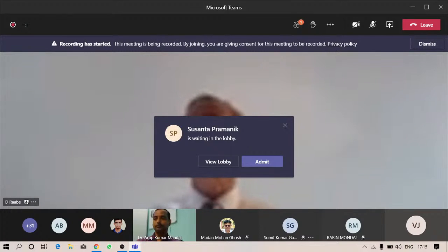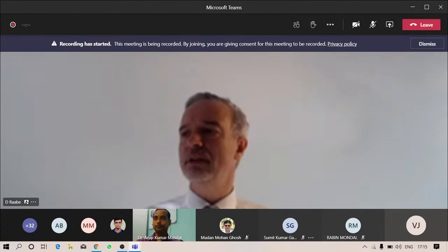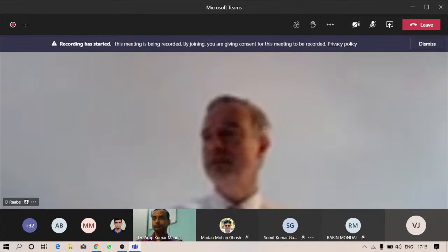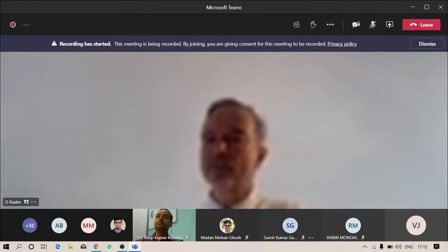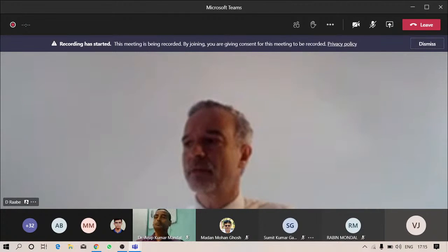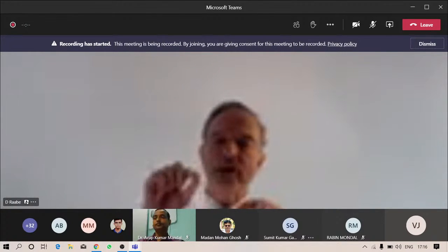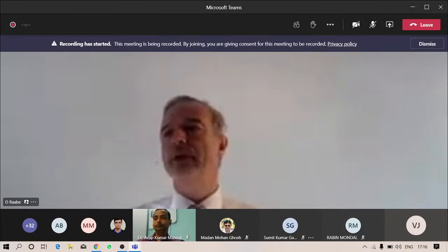When you are very fine in your resolution, like I showed at the very end, where you can do something like a more microtexture-based simulation, then you can, of course, have your local transformation event individually at a certain integration point without interfering with another point that undergoes a martensite deformation. The third refinement method is one that we use in magnesium, where we, of course, do not have TRIP, but we have twinning events massively. And here we do it even more refined, using phase field theory, where you really track the real growth of a twin by a phase field. But this is, of course, a very time-consuming way of doing it and not suited for homogenization. So there are different ways how you can do this in DAMASK with different levels of homogenization.